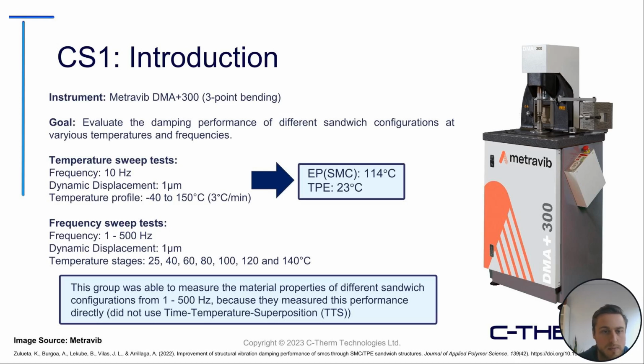They did some temperature sweep tests and frequency sweeps. I won't get too much into the temperature sweeps since we already covered them some, but they found that the sheet molding compound, or composite EP, had a 114 degrees Celsius glass transition temperature, while the thermoplastic had a glass transition temperature at 23 degrees Celsius. This is kind of what they suspected anyways.